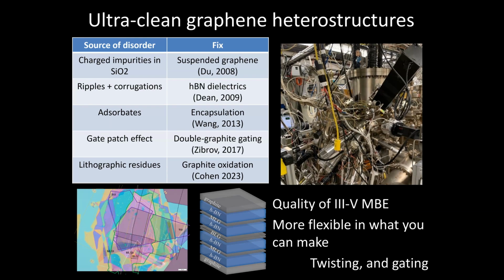But then you can also play with other types of structures, including structures that are not necessarily stable structures that would be hard to grow. So good examples, one of which I'll touch on in the talk today, one of which I will talk about tomorrow, is either rotational misalignments between layers, things that maybe would be difficult to grow, but can change the electronic structure in important ways that give you new physics, or stabilizing things like rhombohedral graphite, which is different from Bernal graphite. Bernal graphite being the graphite that you know, it's AB, AB, AB. Rhombohedral is ABC, ABC, ABC. It turns out it's not that hard to stabilize rhombohedral layers too. And all of these have slightly different electronic structures and can give you radically different types of correlated electron physics or even single particle electron physics.